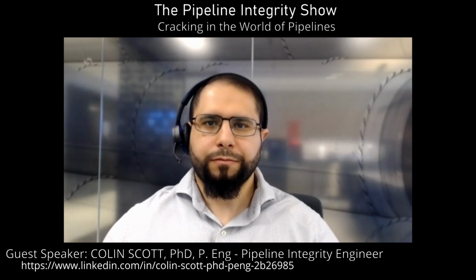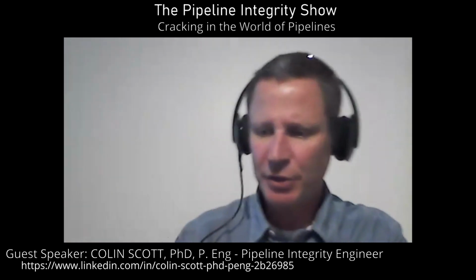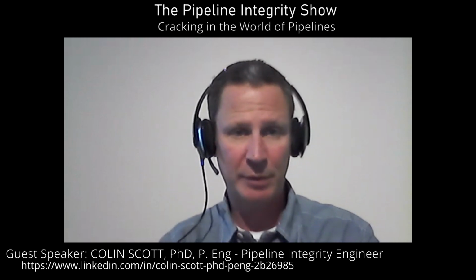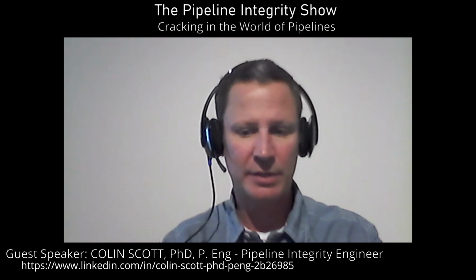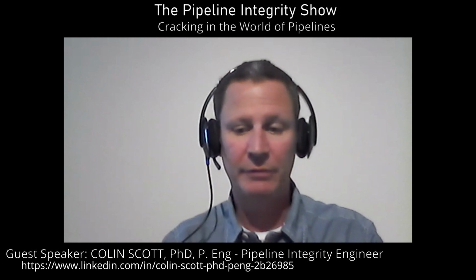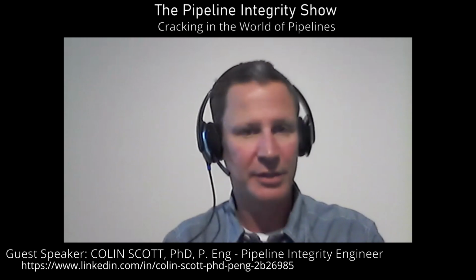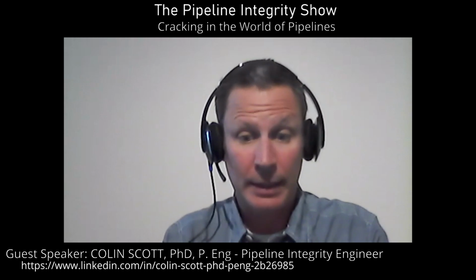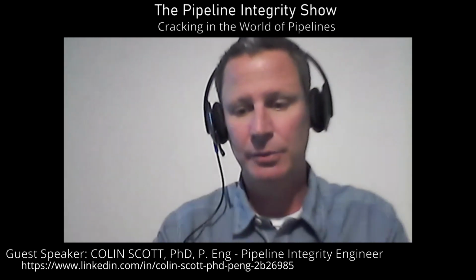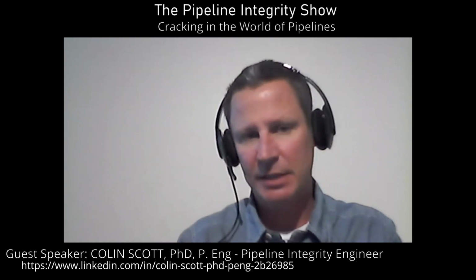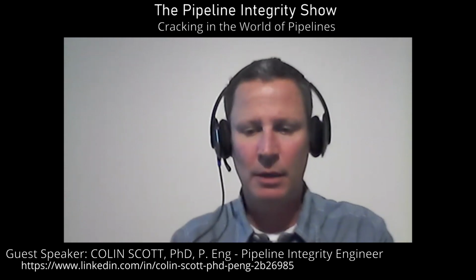Thank you. Okay. So stress corrosion cracking is a difficult one. Typically, you need three things for stress corrosion cracking to occur. You need a susceptible material, you need to have very high stress, and you have to have a corrosive environment. If you have all three of those and all the stars are completely misaligned for you, it can be a stress corrosion cracking issue. Now, stress corrosion cracking has a different mechanism. It's not just about pressure cycling, and it's not just about having some plasticity at the crack tip that's sort of edging a crack along.